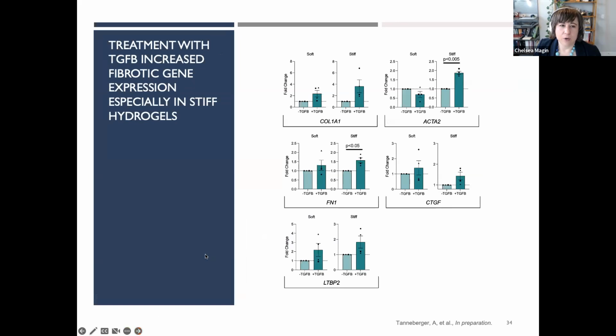If we incorporate what we've done before, so we put these iPSC-derived epithelial cells into a hydrogel that is either soft mimicking healthy lung or stiff mimicking fibrotic lung, along with fibroblasts, we can induce gene expression changes that start to mimic fibrosis, especially in the stiff microenvironments when we add TGF-beta, which is an inflammatory molecule that activates the fibroblasts.